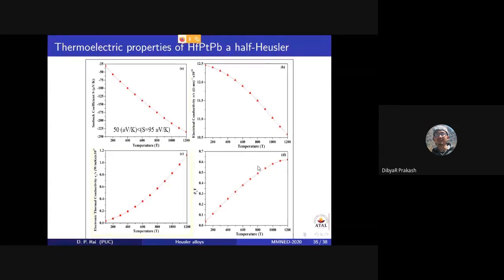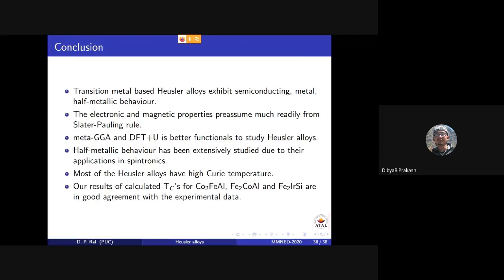So we can say this, our system is a very good thermoelectric material for a higher range of temperature, because ZT, the efficiency, is increasing. So in conclusions, transition metal-based Heusler alloys exhibit semiconducting, metallic or half-metallic behaviors that we can pre-assume from the Slater-Pauling rule. So that is one of the advantages to predetermine. Then we can start our calculations, and electronic and magnetic properties can be easily pre-assumed from this Slater-Pauling rule.